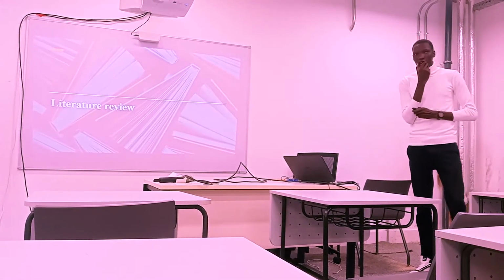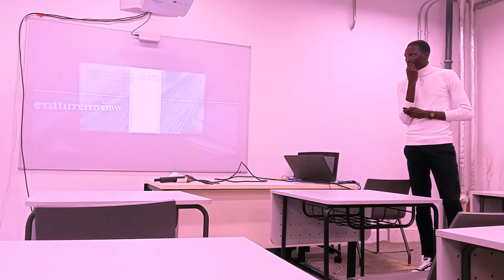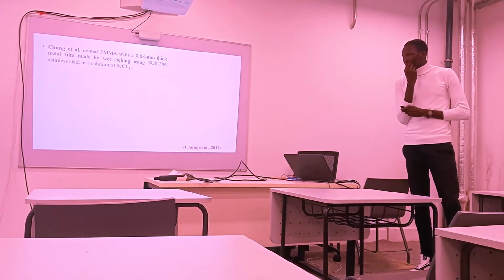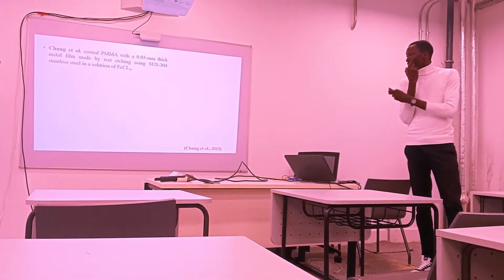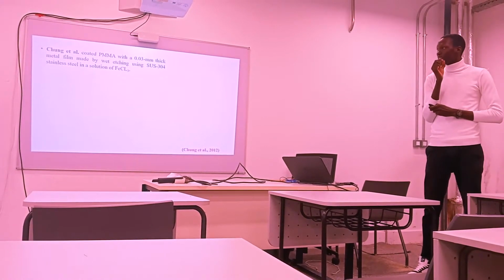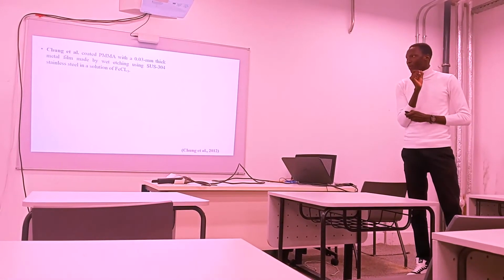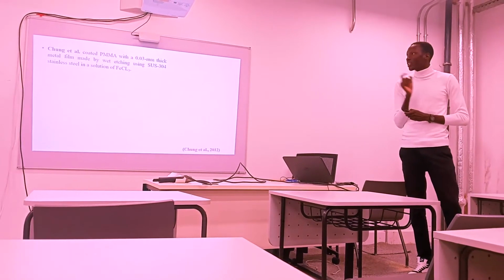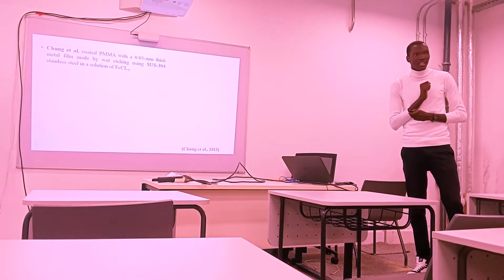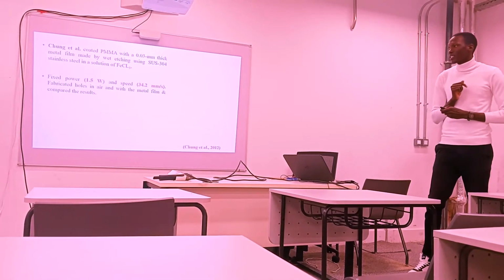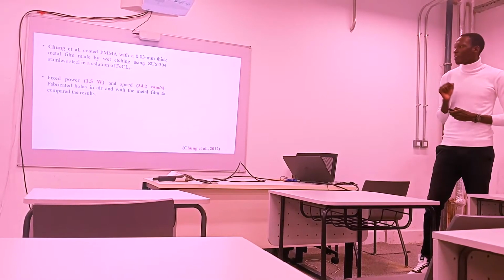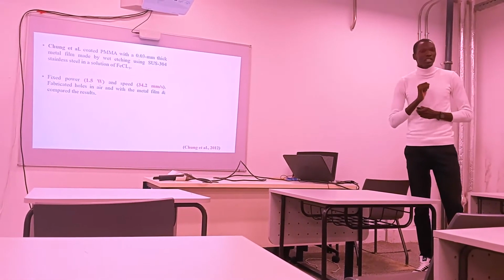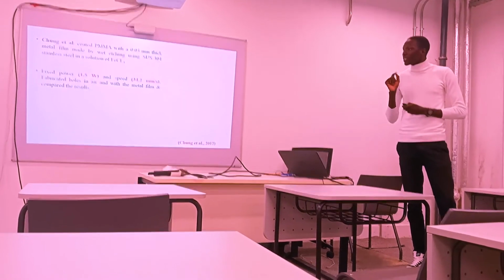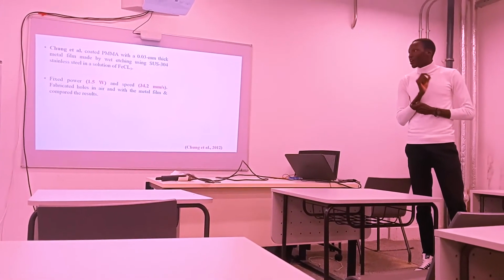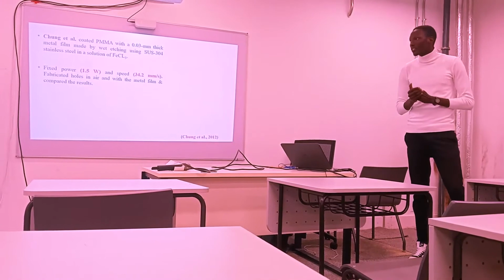We looked at the work done by some people, which is in line with what we were doing. We found Chung and others coated PMMA with a 0.03 millimeter thick metal film made by wet etching using SUS-304 stainless steel in a solution of iron 3 chloride. They fixed power at 1.5 watts and speed at 32.2 millimeters per second. Then they fabricated holes in air and with the metal film, and compared the results. This is what they found.